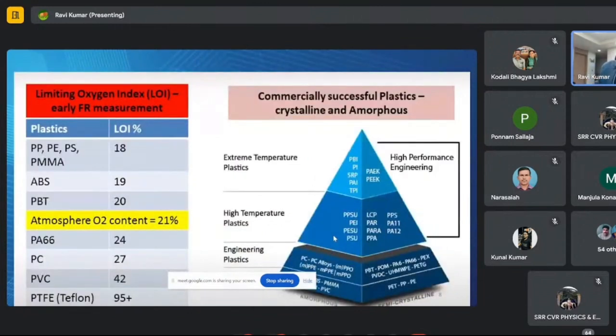Here you can also observe the limiting oxygen index. What is the limiting oxygen index for flame retardant measurement? It depends on the penetration of oxygen into the material that can catch fire and extend the fire until it burns the last piece, or last atom, of the material. To address that, we have tabulated the LOI percent here. For the plastics, polypropylene, polyethylene, polystyrene, and PMMA, the LOI is 18%, ABS is 19%, PBT is 20%. The atmospheric oxygen content is around 21%. That's why they catch fire immediately.